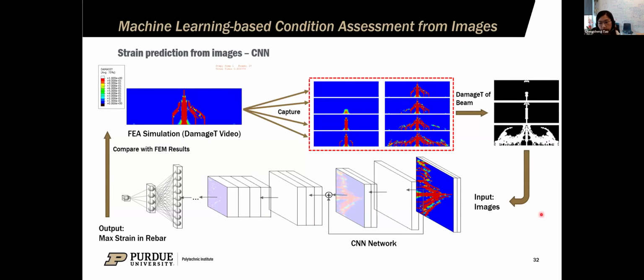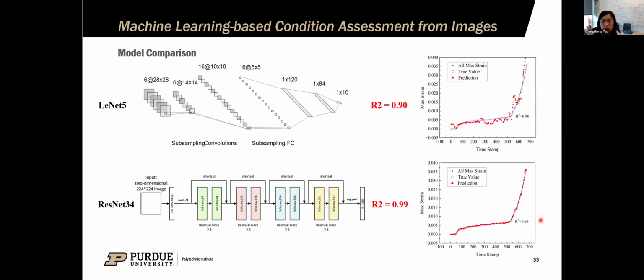We input them into the CNN network and output the maximum strain in the rebars. Here, we used two different CNN structures, LeNet-5 and ResNet-34. LeNet-5 is a relatively small model which has 5 layers and more than 60,000 parameters. For the first structure, the R-square value is about 0.9. And then we also use ResNet-34. It's a bigger model which contains over 20 million parameters, and it generates a higher R-square value for the strain prediction.